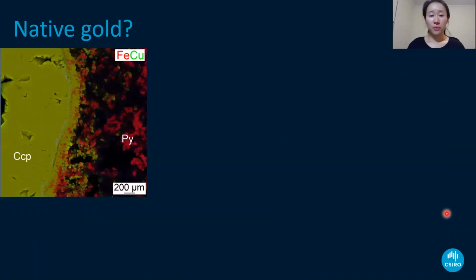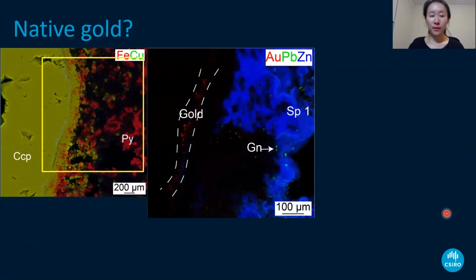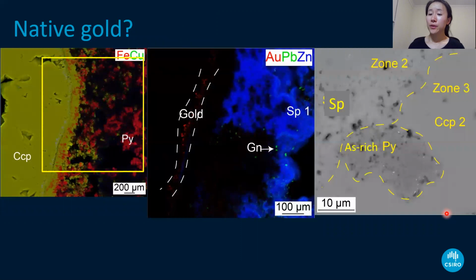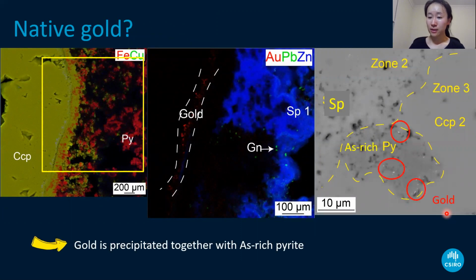Then we took a look at the second type, where gold occurs on the boundary of the chalcopyrite wall. The SEM image shows us two different gold occurrences. So gold occurs together with arsenic pyrite. You can see the gold particles on the arsenic-rich pyrite. This is very commonly observed in hydrothermal gold deposits. We all know that during arsenic pyrite precipitation, the arsenic can help to accumulate gold into the pyrite. So here we interpret that gold is precipitated together with arsenic pyrite during the fluid mixing.